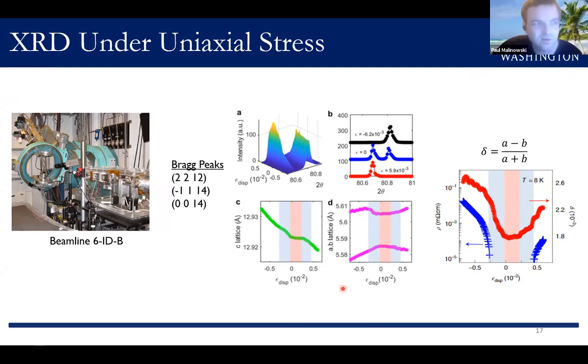In terms of which way we're moving the phase diagram, you can think of it as enhancing orthorhombicity. So it's a little bit complicated. That means you're pushing to the left, right? Yeah, you're pushing to the left. You're saying that maybe we are inducing antiferromagnetic order. At least in the optimally doped composition, we don't see that. But in the underdoped sample, there's already static antiferromagnetic order, and it's clearly enhanced under the strain. We're enhancing that.